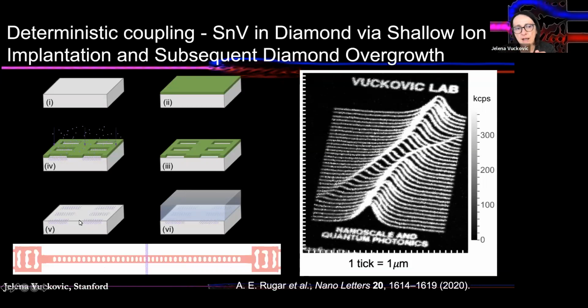But of course, your tin atoms or silicon atoms end up being very close to the interface, which means that you have to regrow high purity diamond on top. We managed to perfect this method so that we right now have these impurities implanted by these methods that are comparable in properties to even naturally occurring impurities in the material or CVD grown ones. And we can incorporate them at desired positions anywhere we like, even in the shape of my group's logo, right? This is luminescence from tin vacancies on a chip. I mean, it's not really useful for anything, but it shows you that we can completely control their positions.